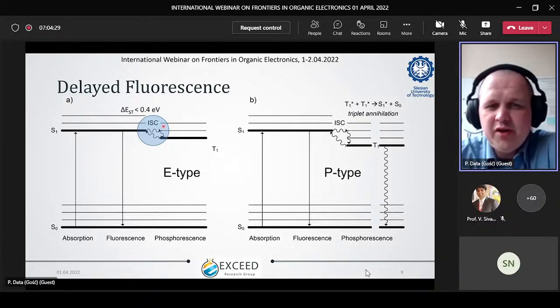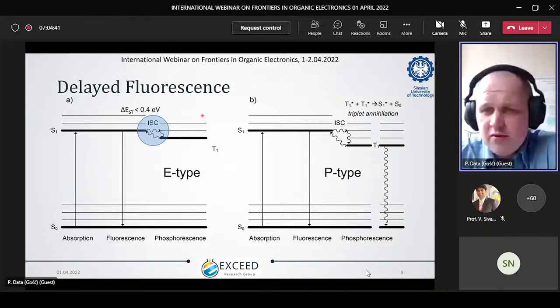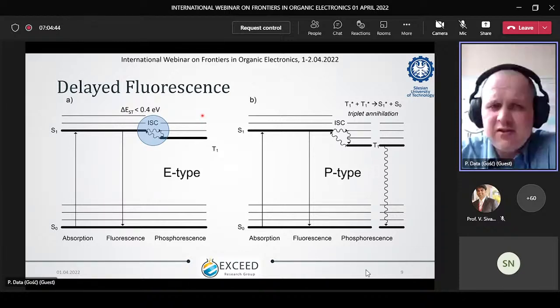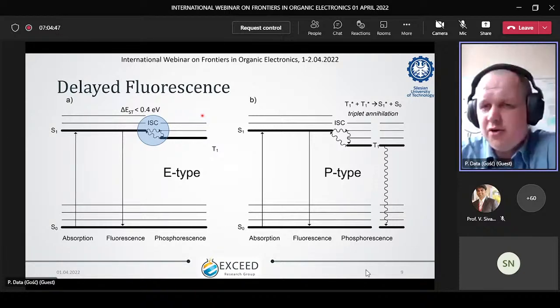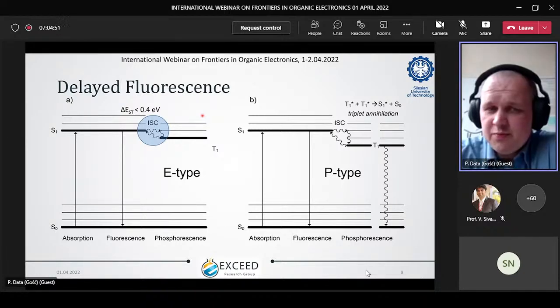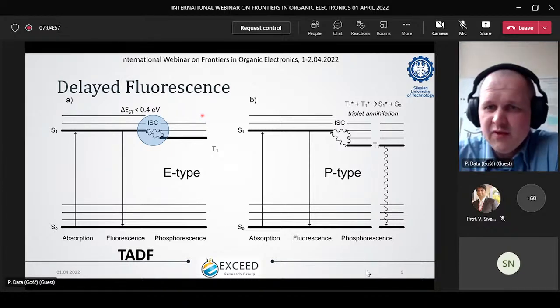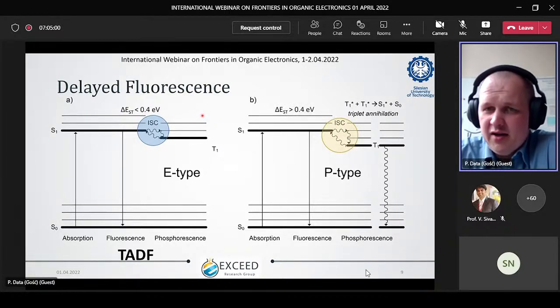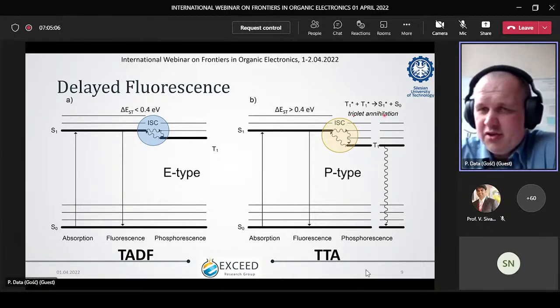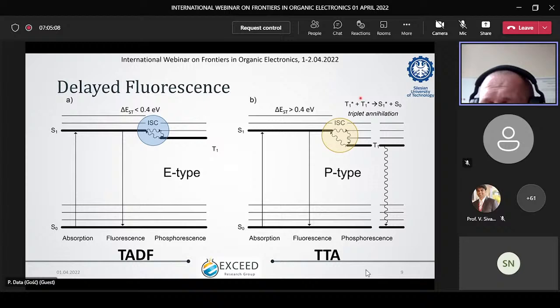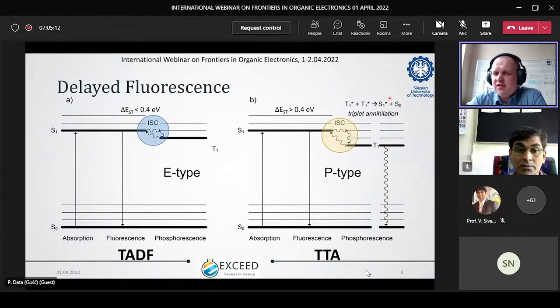And from experience and the literature, you can find that to have efficient transfer from the triplet to the singlet state, the gap should be lower than 0.4 electronvolt. Why 0.4 electronvolt? Because in general, this is the energy which you can harvest at room temperature from the heat. And that's why this process is also called TADF, which means thermally activated delayed fluorescence. The other process, where the gap is higher, is called triplet-triplet annihilation, the TTA process, where we need to use two triplets which annihilate and form one singlet excited state.